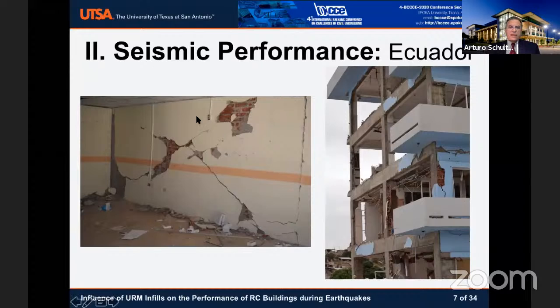Here are a couple of examples. On the left, you see an interior wall. You can clearly see the clay masonry. You can see the diagonal cracking that has formed, obviously on the cover that has been placed on top of the masonry, but that is there, of course, because the masonry has also cracked. And you also see spalling in regions where compression damage has begun in the masonry. So this is very common. Now, if the earthquake stops at this point, there is a chance you may be able to somehow repair this. But if it goes on longer and these cracks become wider, then there is a high likelihood that this wall can collapse out of plane because it has no support anymore.